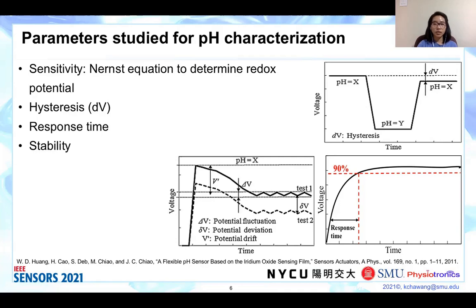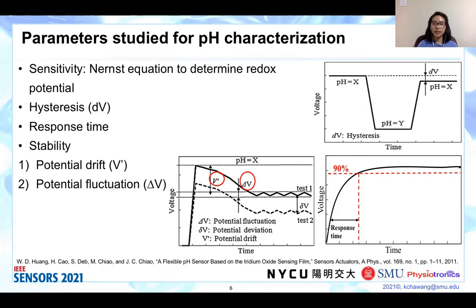First, we define potential drift. It is the difference between the peak and settled potential. Second, potential fluctuation. The worst potential fluctuation is maximum change in settled output potential. Potential deviation, it is the potential difference between different test cycles tested in the same solution. Test 1 in our case means it follows the sequence of pH 2, 4, 7, 10, 13, 10, 7, 4 to pH 2.